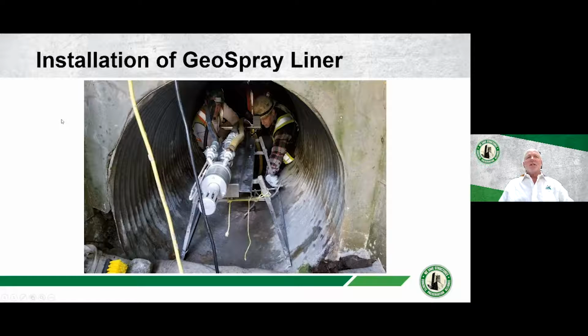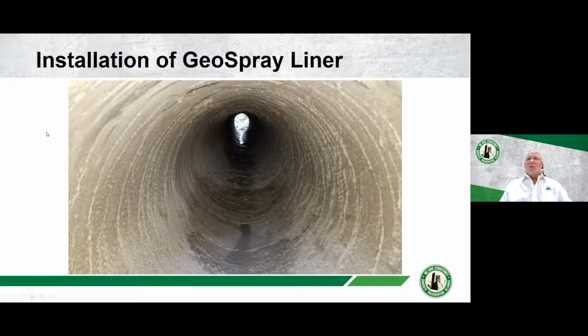Here's the setup. Guys are getting ready to spray. You can see the spin caster set up on the sled. Again, the calculations have been done, knowing the amount of material that was going to be coming to the spin caster, knowing the size of the pipe. We have a variable speed winch that pulls back the sled at a consistent speed to get you a uniform layer on the inside of the culvert. Here's a look at the inside after it had been sprayed. So you can see a very, very effective lining system that's going to extend the life of the culvert.